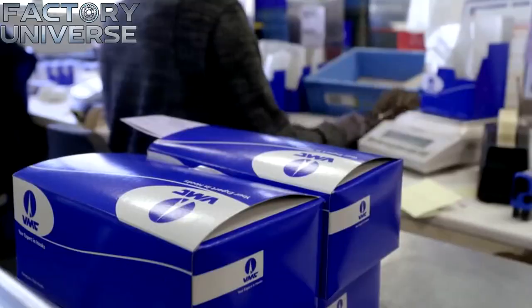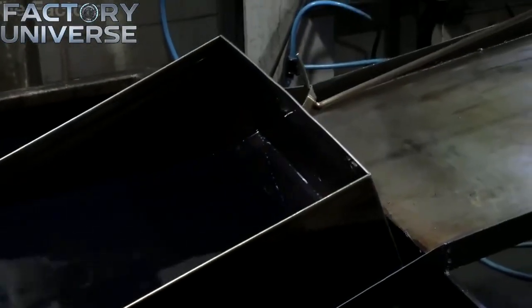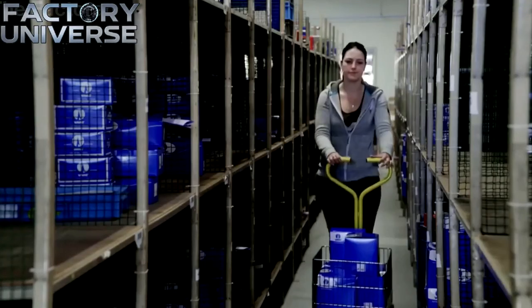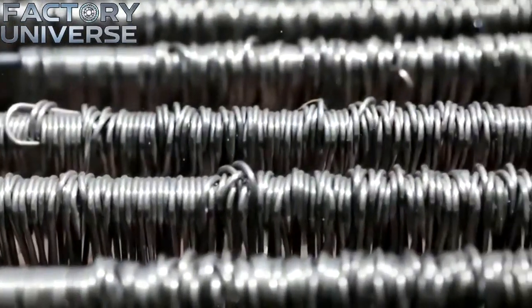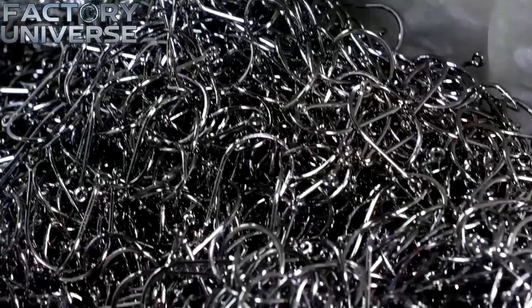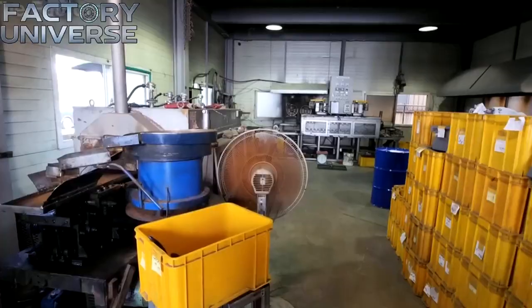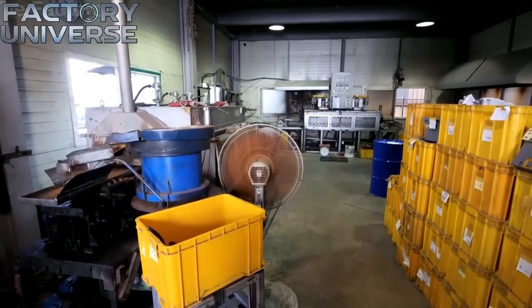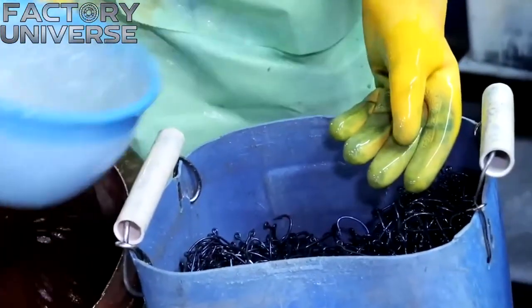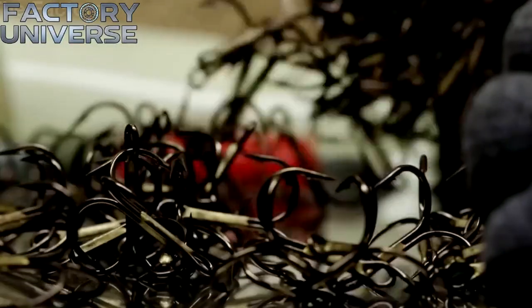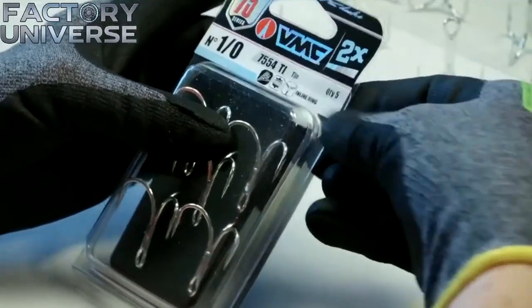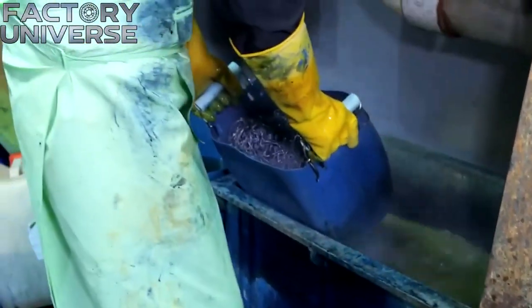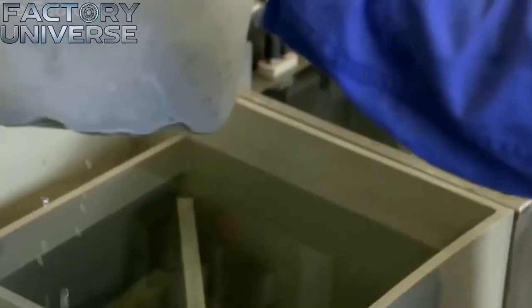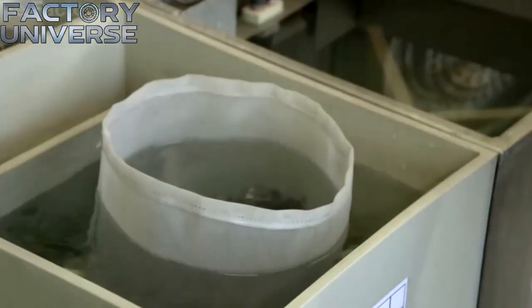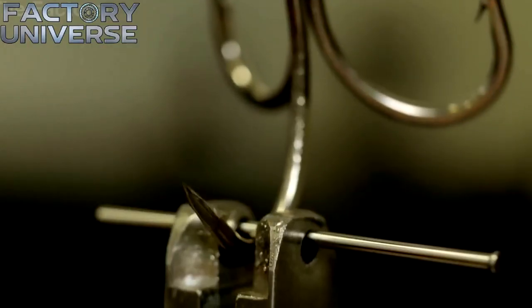The hooks move along the metal conveyor with the mechanical precision of a clock. One can notice how the material transitions from the furnace directly into a controlled cooling environment. This rapid quenching locks the newly formed microscopic structure into place, resulting in a dramatic increase in hardness across the entire surface. It looks superficially simple to harden the steel in this way, but in reality, this state creates extreme brittleness. A hook that is only hardened would fracture like glass under the sudden tension of a moving weight. The process is only gaining momentum as the items proceed to the tempering phase.